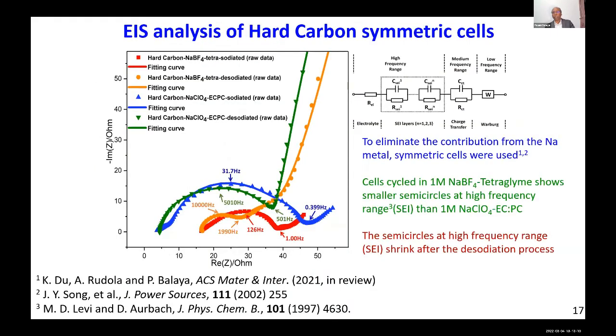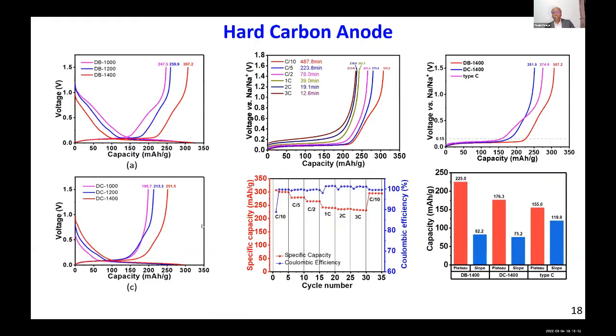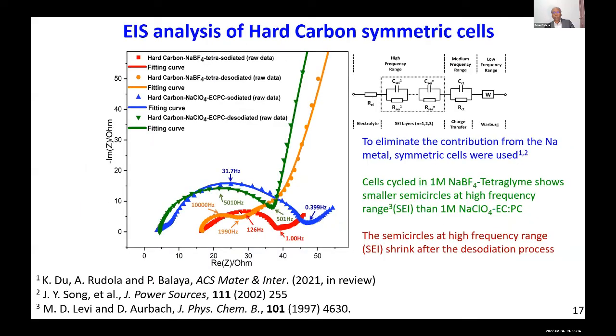And this is a very good example of so-called internal resistance. When you are inserting sodium into hard carbon, you can see here the diameter of the semicircle is much lower than the blue one, which is the sodiated hard carbon using carbonate-based electrolyte, which tells you that the internal resistance associated with the sodiated hard carbon and desodiated hard carbon using tetraglyme is much less as compared to carbonate-based electrolyte. So we have several convincing arguments that tetraglyme is a way to move forward.